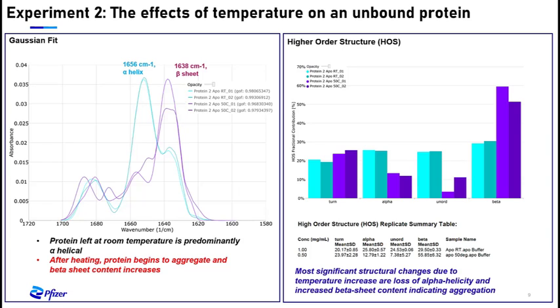On this last slide from experiment 2, I'd like to show you the last bit of data. That is a nice summary of our experiment where we've looked at the effect of temperature on our 47,000 Dalton protein. Higher order structure is calculated by the Gaussian curve fitting on the left. This nicely shows the shift from alpha helical to beta sheet structure in our protein after heat treatment. And this is expected since the temperature in the heat treatment is close to our empirical Tm.